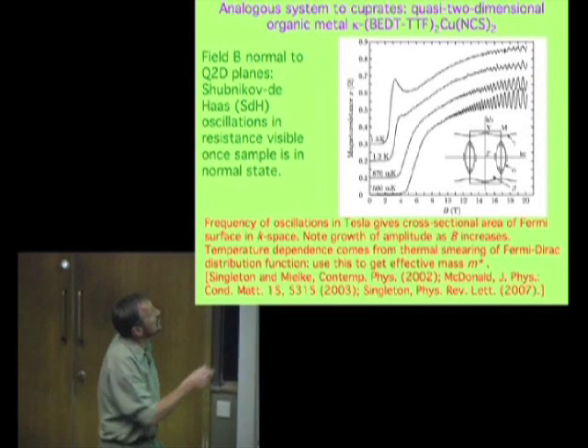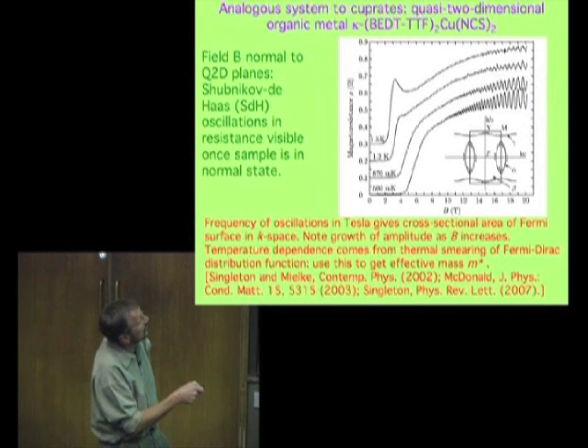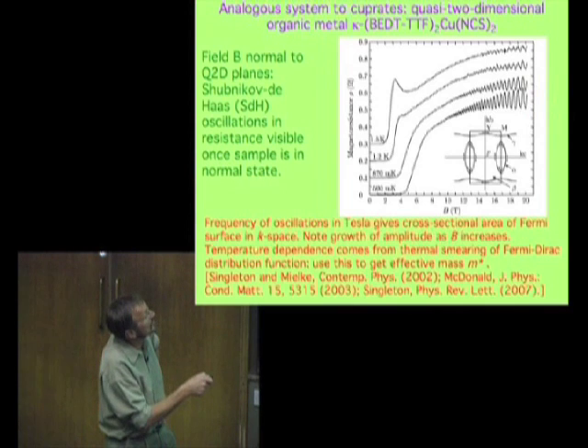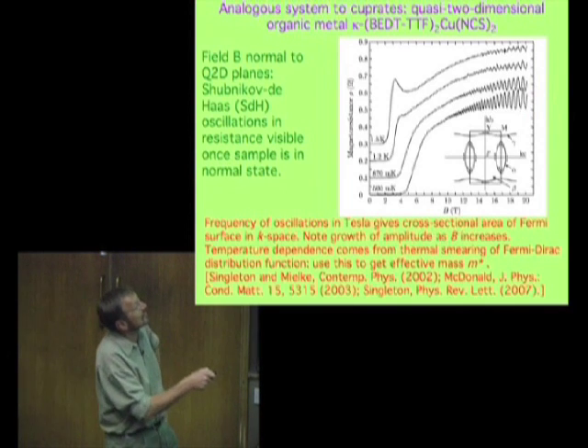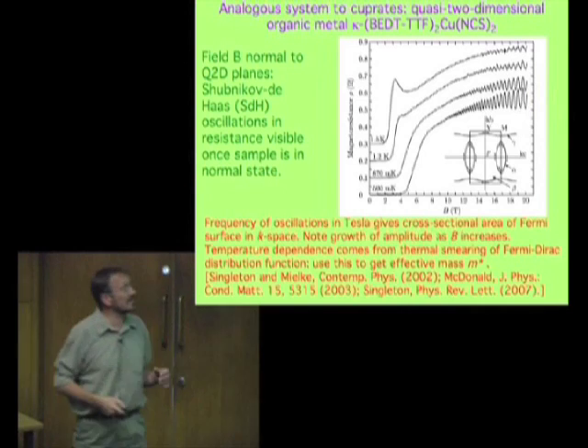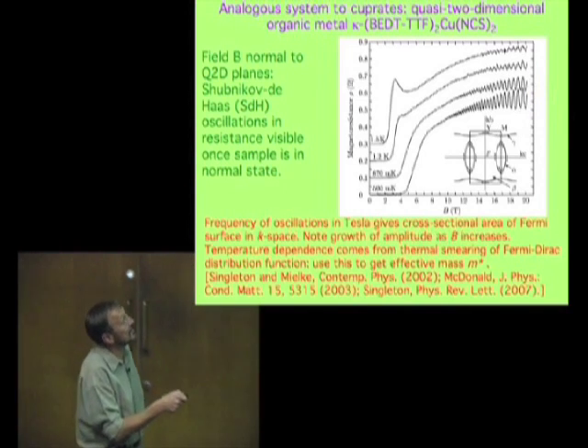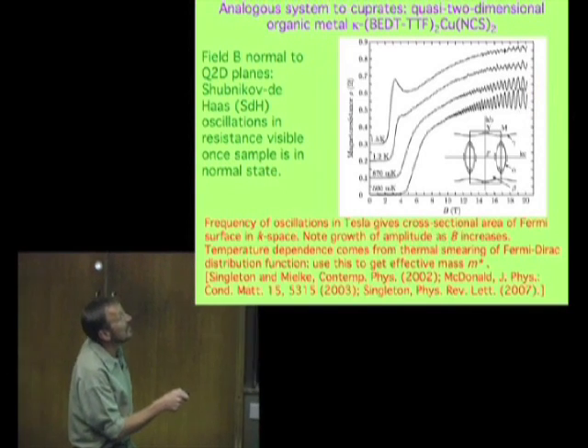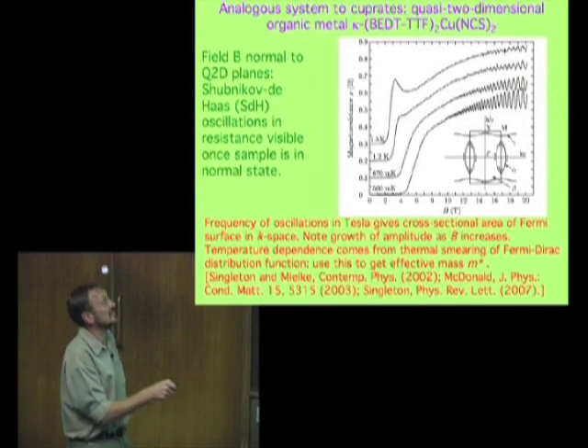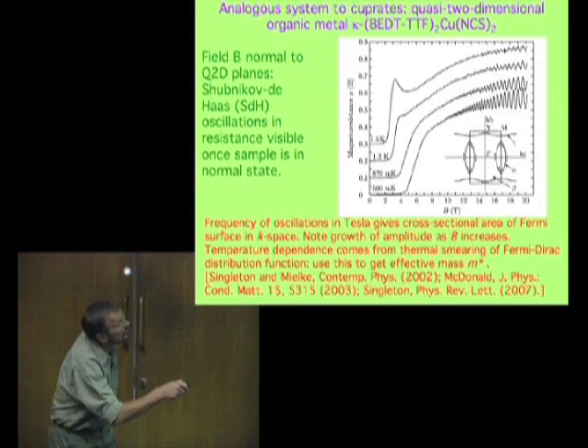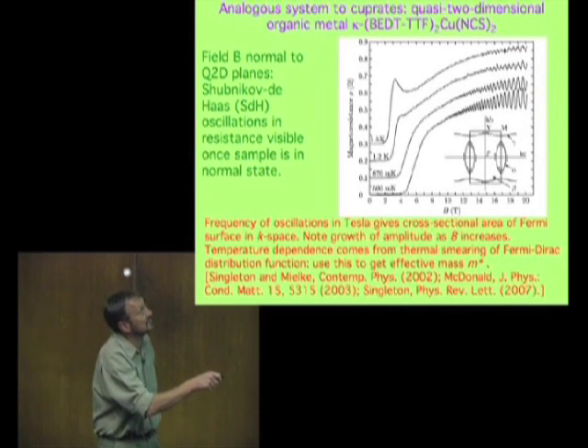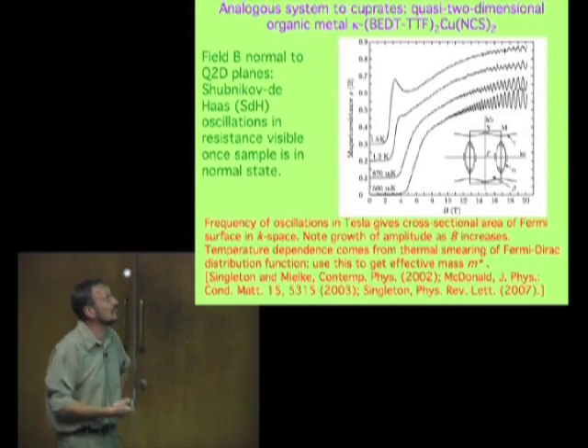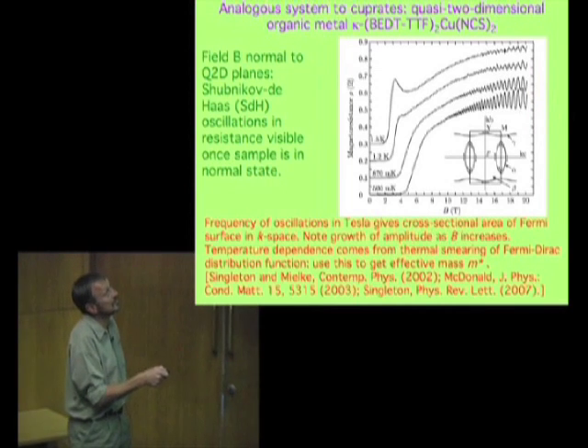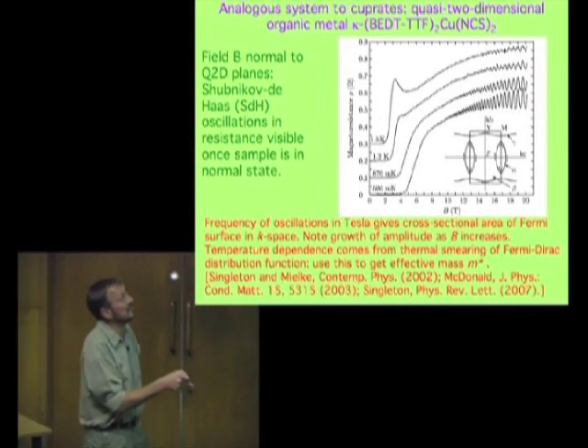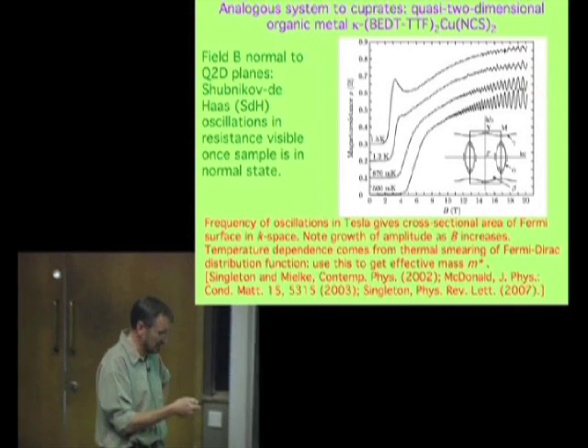Here we've got the resistance as a function of the magnetic field. The thing starts off a superconductor, goes into the normal state, and then we get these oscillations. The first thing that you can get out of these oscillations is that they're periodic in 1/B, the magnetic field, and the frequency of the oscillations in Tesla gives you the cross-sectional area of this Fermi surface section here. So without any other assumptions, we can straight away measure the cross-sectional area of the Fermi surface from these oscillations.